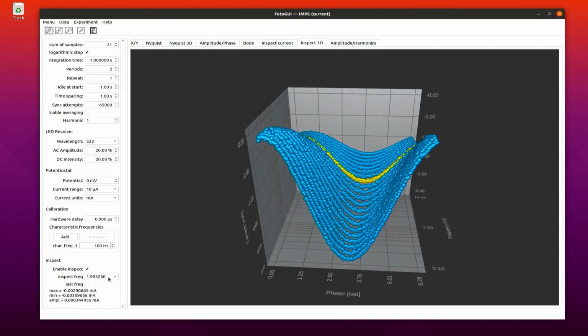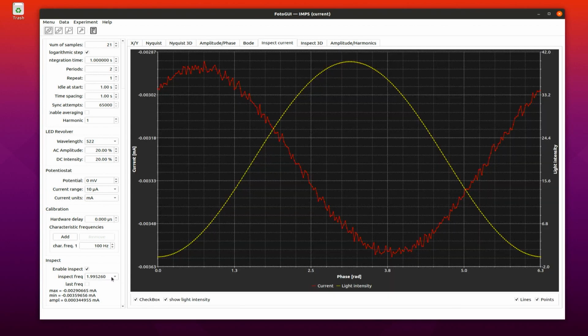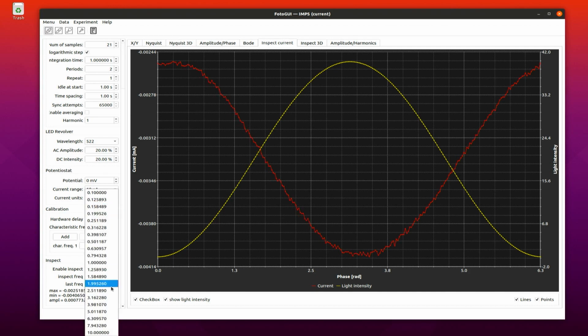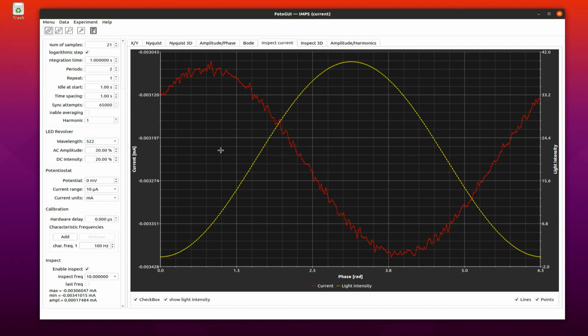We can mark any of these curves. From the slowest, here is the incident light, and here is the current value. These values are negative, and the faster the signal changes, the delay is larger. And the amplitude is also decreasing, but in this graph it is rescaled to full screen, and you can only see it by following these values.